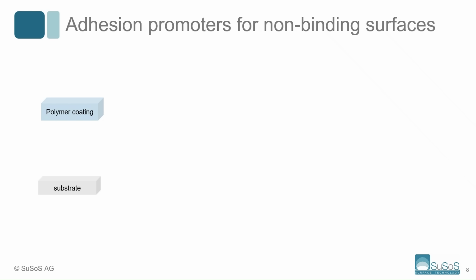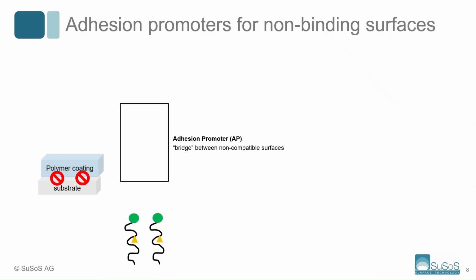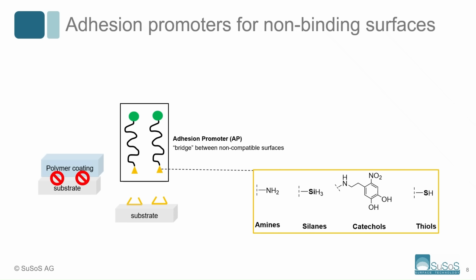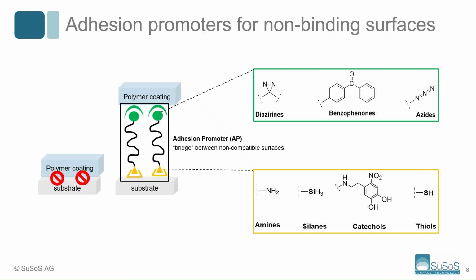Of course, we already know that there are various substrates and add layers, so the materials that we want to deposit on the substrates. For example, we want to bind glass with nanocellulose, glass with glass, or steel with nanocellulose. And very often the compatibility and possibility to bond them without functionalization is impossible. In that case, we need to find a bridge, the adhesion promoter, that will on one side anchor the add layer to the according substrate, and on the other side of the adhesion bridge bind the add layer, the additional coating that we want to put.